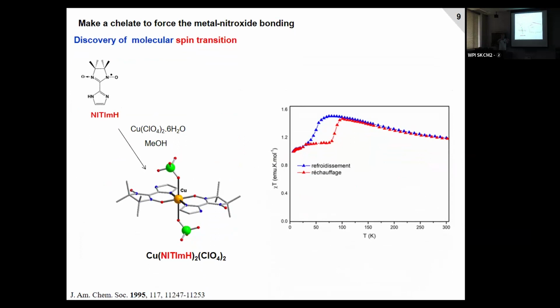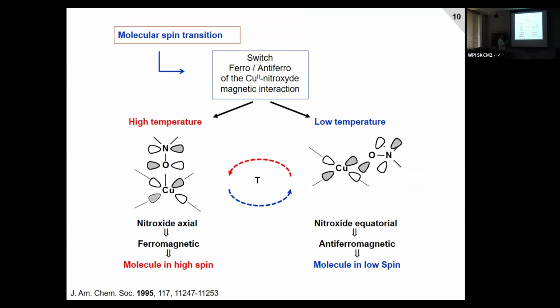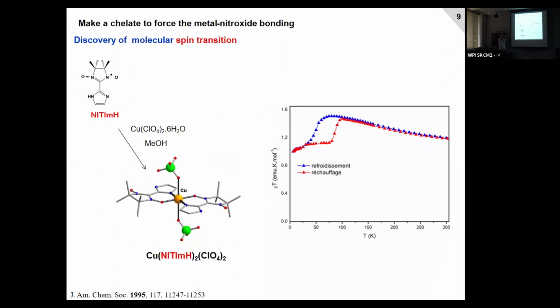In fact, we have studied the crystal structure at room temperature. This is the room temperature. The plane of the radical here and the plane of the x2-y2 orbital of the copper are coplanar, completely coplanar. So in that case, you favor ferromagnetic interaction. But when you go to low temperature, there is a small distortion of the ligands regarding the copper. So you have no more coplanarity, and the interaction becomes anti-ferromagnetic.